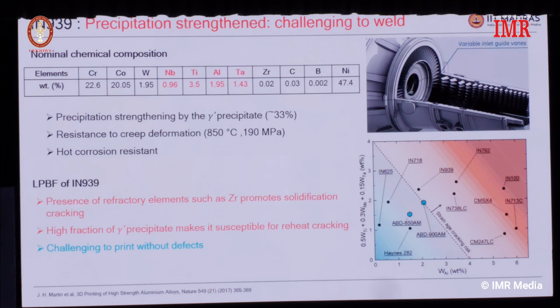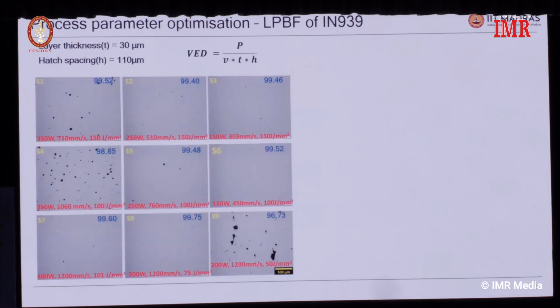Anything above this 45 degree line is very difficult to weld, which means it is very difficult to additively manufacture. Below that line are easily weldable. The same strengthening that gives its high temperature properties is responsible for the lack of easy weldability, or easy manufacturability, of this particular alloy. But we have to deal with it.